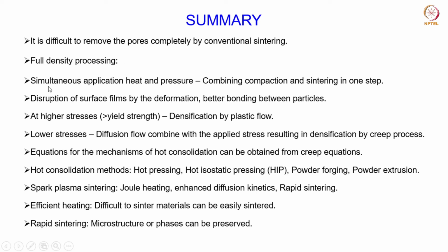So full density processing basically is a method which applies the heat and the pressure simultaneously. So this is kind of combining the compaction and the sintering process in one step, unlike the conventional sintering process in which the powder is first compacted and then the green compact is separately sintered to achieve densification, right? But in this case, the powder can be directly sintered with the simultaneous application of heat and pressure to fully densify it. Okay, and the process which basically leads to this enhanced densification is the disruption of the surface films by the deformation that takes place at high temperature, right?